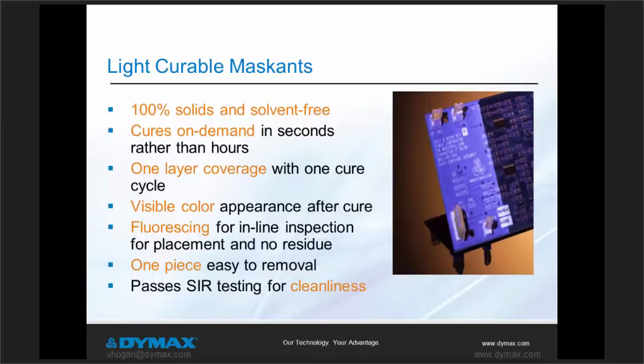Unlike the latex-based maskants, light-curable maskants cure on demand in seconds rather than hours, which means the boards are readily available for your conformal coating process. There is no need to rack your boards to wait for the maskant to cure. The light-curable resins are applied to the necessary thickness with one layer of coverage with one cure cycle. Additionally, these resins are formulated with fluorescing agents for inline placement inspection, just as Chris had mentioned about the conformal coatings. When properly cured, the resins can easily be removed in one piece after the conformal coatings are tack-free.